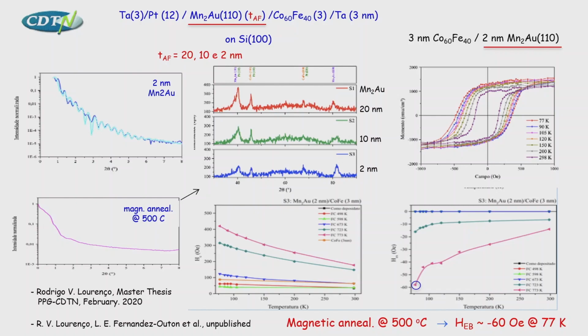We are playing with the thickness of the antiferromagnet. Before we were using an antiferromagnet with 20 nanometers. Now we went down to 2 nanometers, and we see that we get the same exchange bias doing the same kind of treatment. That means it's a little bit small, very disappointing, but